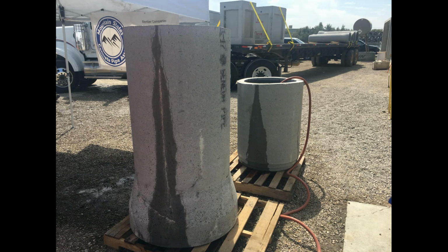That was from 3 weeks ago. That's all it took, was 3 weeks for that to start forming and filling and sealing itself up. Now, you can see that there's still a little bit getting through that pipe, so it's still leaching. After 3 weeks, it's still going a little bit through there. But keep in mind, this is a pretty big, significant crack, all right? And as it goes in and seals, this is just after 3 weeks of being filled with water, okay?